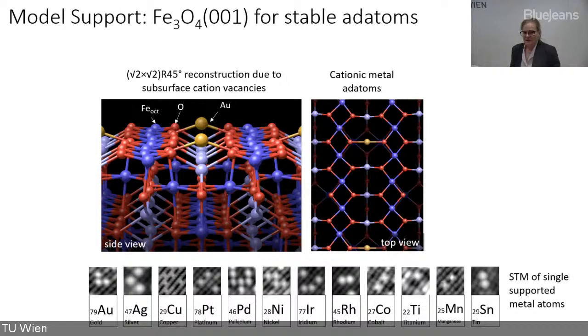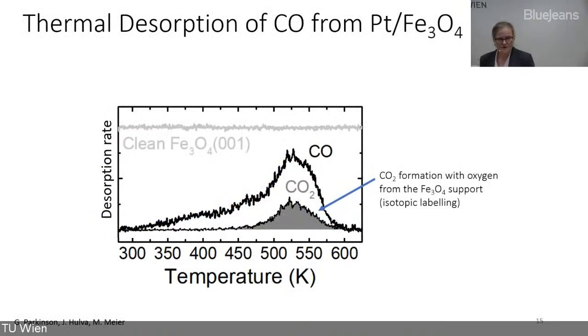Next, I want to show you some results with platinum. If you take platinum atoms and put them on the surface - I already mentioned platinum is a good catalyst, for example for CO oxidation - this here is a thermal desorption of carbon monoxide. Carbon monoxide is very often in surface science a simple test molecule to study a relatively simple catalytic reaction.